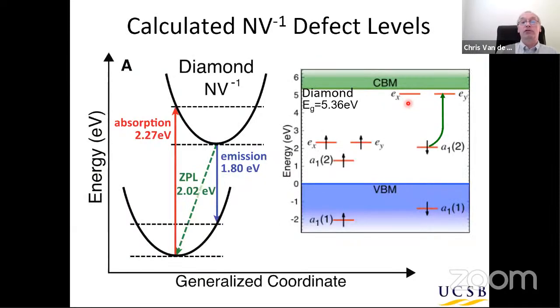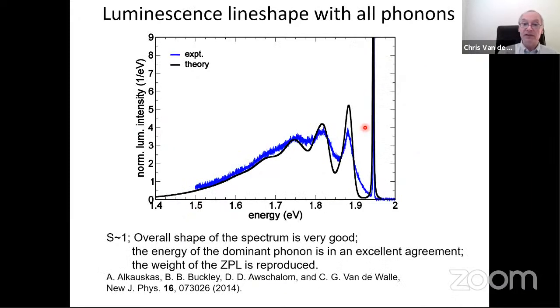So just to return to the NV center, we've done this sort of calculations also for the NV center in diamond. Here's the configuration coordinate diagram. We can calculate absorption and emission energies, and we can actually also calculate the luminescence line shape, which is quite difficult in that case. My collaborator, Audrius Alkauskas, did a great job on this. And as you can see, you can actually model the line shape quite well, including all these intricate oscillations that are observed due to interactions with specific phonons.